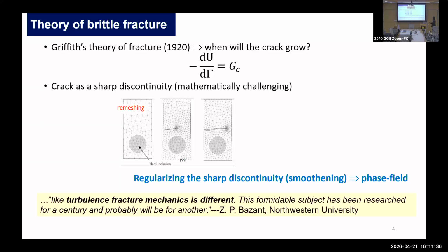One of them is if we just model the crack as a sharp discontinuity, that is what it is actually. In reality, a crack forms as a sharp discontinuity, and those of you who are dealing with continuum mechanics probably know that all our equations in continuum mechanics are based on a critical assumption that everything is continuous. So our displacement field and strain and stress, everything is continuous, and we have a very easy solution scheme, energy minimization. But the moment a sharp discontinuity forms, those assumptions become invalid, and we have to do special treatment to represent those discontinuities and still work in the realm of continuum mechanics. So people have been doing that.